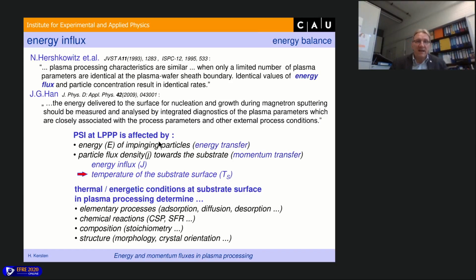And at the end, as I mentioned, during this plasma surface interaction at low pressure plasmas, you have the energy of the impinging particles. This is the energy transfer, and you have also the momentum transfer by the particle flux. And at the end, it results in the surface temperature or the equilibrium temperature. And this temperature influences again the different elementary processes at the surface, as I mentioned in the beginning. For instance, it influences the adsorption, the diffusion, the desorption of the species at the surface, the chemical reactions, the composition and stoichiometry of the growing film, and also the structure, the crystal orientation, the morphology, and so on. So it is really interconnected.